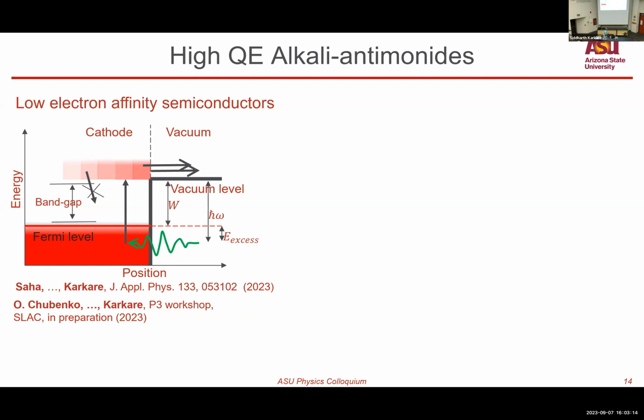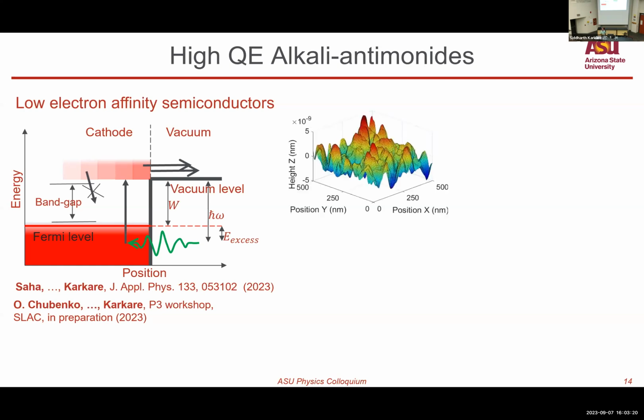However, they have one issue, or rather used to have one issue. Their surfaces were very rough. They're usually grown as thin films, traditionally using a sequential deposition technique where people would deposit a thin film of antimony, then a thin film of cesium, and it would react on the surface, producing a thin film of cesium antimonide, or even potassium cesium antimonide. And that produced a very rough surface.